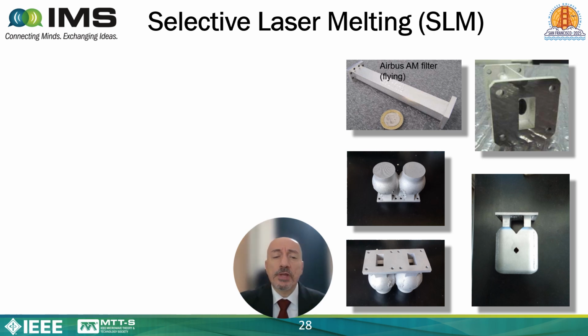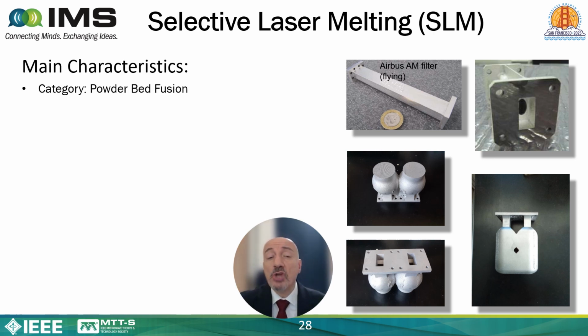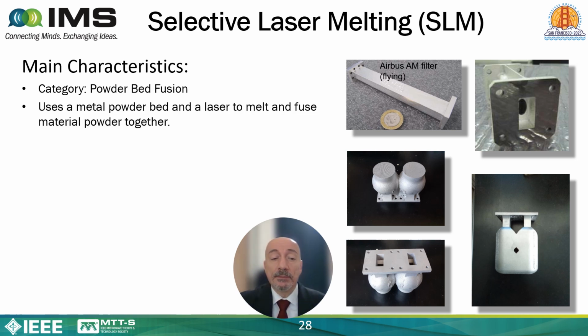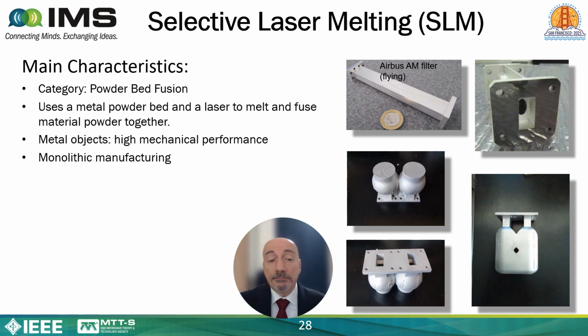And let's now see a technology that falls in the category of powder bed fusion we just described. This is the selective laser melting. In this case, we have a metal powder and a laser to melt and fuse the material powder together. This means that we obtain a directly metallic object, and this results in high mechanical performances. And we also can manufacture it monolithically, and this is another great advantage because in this case, we don't need to manufacture the object in two halves because we don't need to metallize the internal part. So we can manufacture directly monolithically, and this is an advantage from the point of view of the weight of this object, because if you manufacture in two different parts, then you have to assemble them together, and you need flanges,